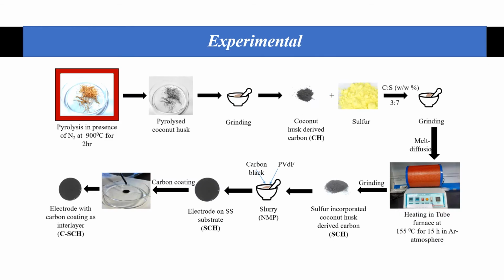The experimental work includes pyrolysis of coconut husk at 900 degrees C in a nitrogen ambience for 2 hours, and then the ground coconut husk was mixed with elemental sulfur in the weight ratio of 3:7, followed by heating in a tubular furnace at 155 degrees C for 15 hours in argon ambience to enable the sulfur impregnation in the carbon matrix. Later, carbon black and PVDF were used along with the composite to prepare the slurry using NMP as a solvent, and then it was coated by doctor blade on the stainless steel substrate, and then the carbon coating was applied using candle soot over carbon, and these electrodes were used for electrochemical testing.